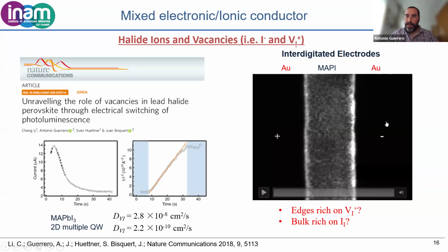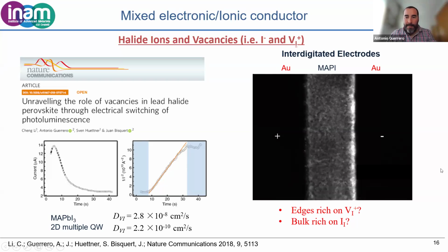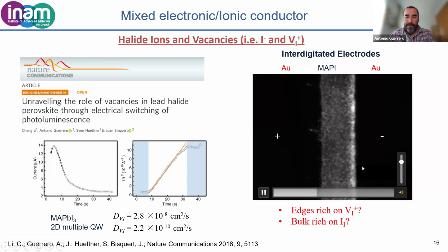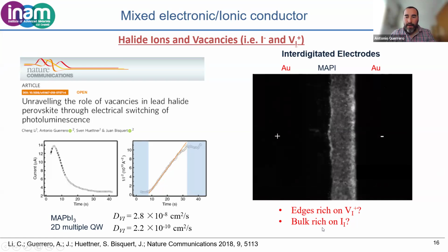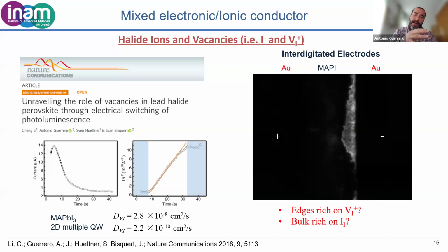So this is gold electrode, this is gold electrode, and here we have the methyl ammonium lead iodide. We characterize the material using PL confocal microscopy, and also as we are applying some voltage, we can also record the current. And if we do that, what we observe is that as time passes, there is a dark front advancing. So the PL gets quenched, and this is because these ions are moving, and we are generating recombination centers.